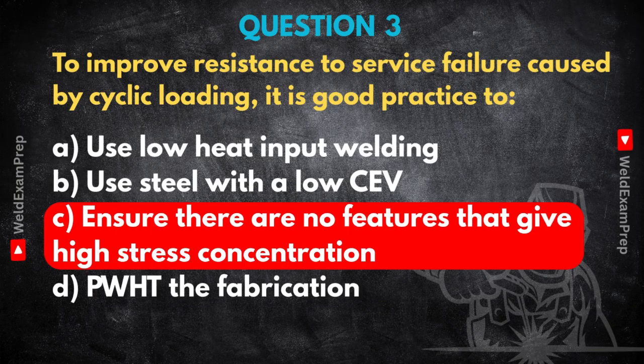The problem is, even if the overall stress in the part is low, at these points, the stress gets magnified. Under repeated loading, this leads to tiny cracks forming and then growing, until failure. So the most fundamental thing you can do is design and fabricate to eliminate those stress raisers. Smooth transitions, good weld profiles, avoiding sharp notches, that's paramount for fatigue life. You know, that point about stress concentration is so important. It really drives home that quality isn't just the weld metal, it's the whole picture: design, geometry, finish. It's a holistic view.